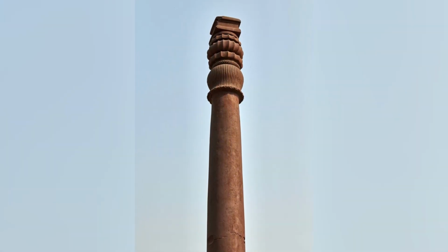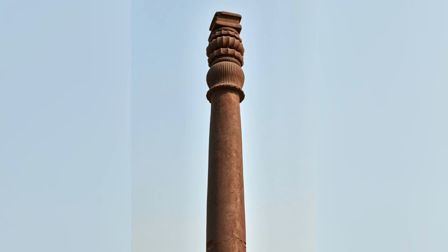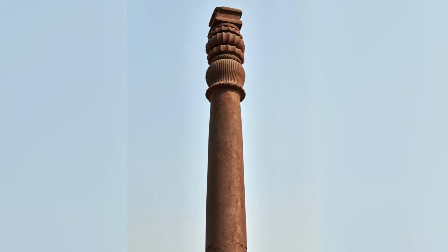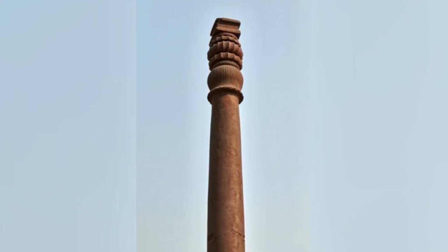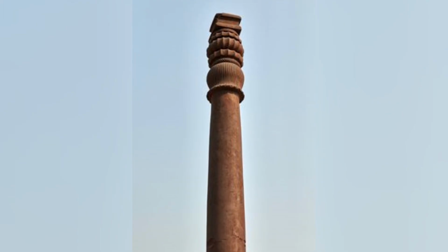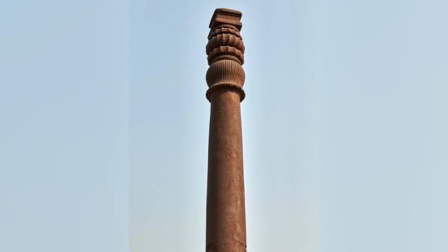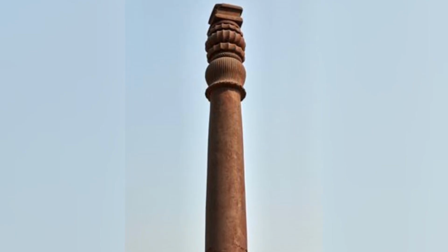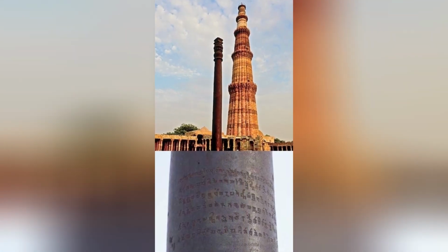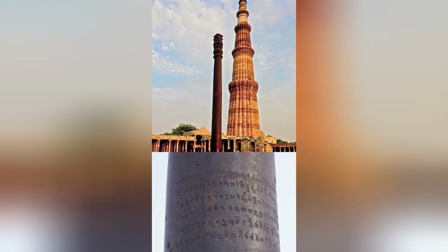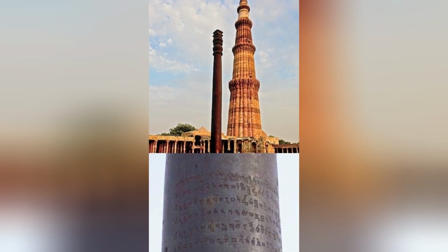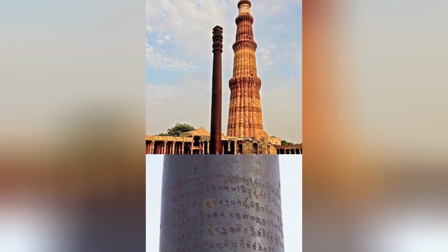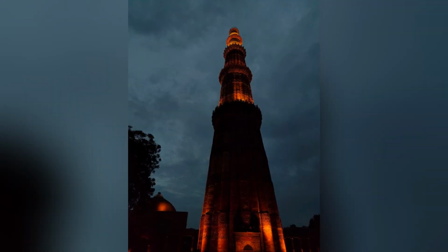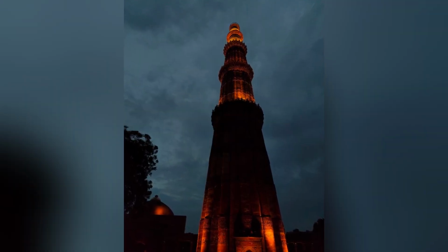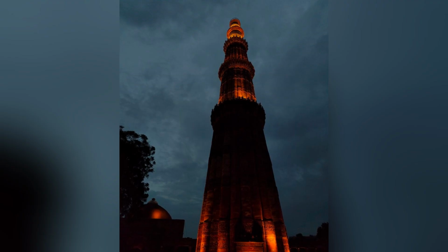The phosphorus content of the Delhi pillar's iron, approximately 0.25%, is significantly higher than the phosphorus content of most modern steels, but it is within the range of phosphorus contents that have been measured in other ancient Indian bloomery irons. The analysis of iron objects from archaeological sites across India has revealed that the phosphorus content of Indian bloomery iron varies widely from less than 0.01% to more than 0.5%, depending on the specific ore that was used.